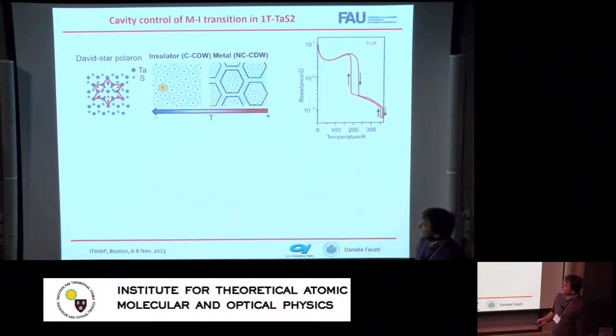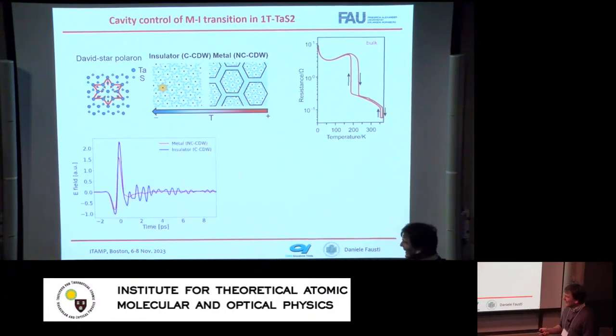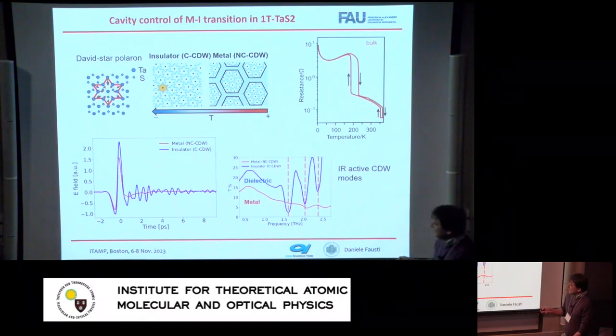The setting works, and the first interesting problem that we studied is a charge density wave material, tantalum disulfide, known to the community in many different aspects. I haven't seen it in this conference, but it will pop up soon, I'm pretty sure. We chose an observable. For us, the observable was terahertz spectroscopy, and we could actually see the weakness of this metal insulator transition, in the sense that the terahertz transmitted in the metallic phase is essentially featureless, while the terahertz transmitted in the dielectric phase has very sharp resonances. You can look at the resonances directly.